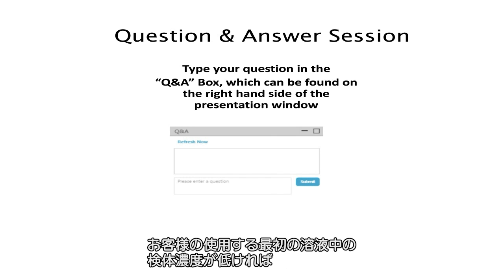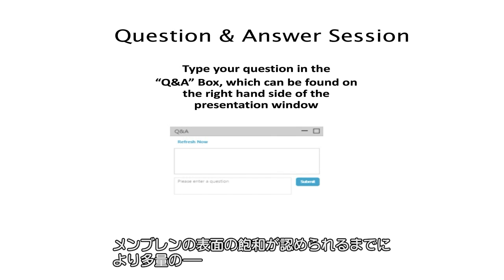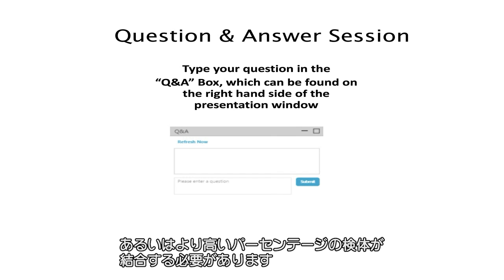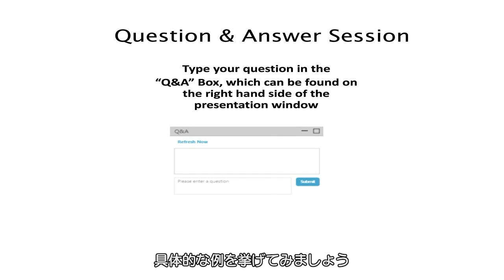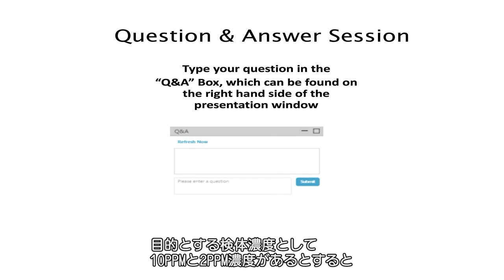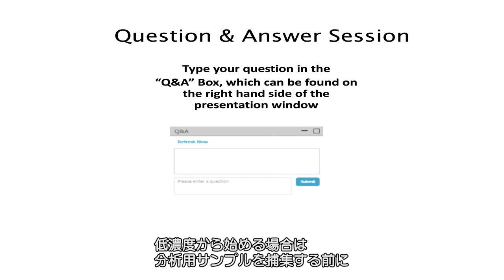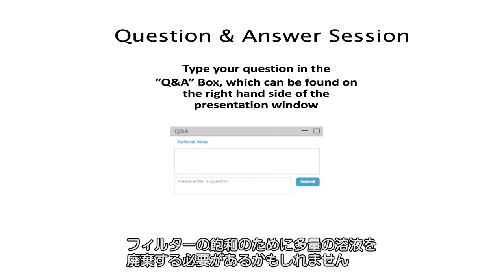If your initial concentration of analyte in your starting solution is lower, then it means a higher percentage of your analyte would need to bind before you can see full saturation of your membrane surface. So what this means in practical terms is, say for example, you are working with a concentration of 10 ppm versus 2 ppm for your analytes of interest. You might have to discard a larger volume of the solution before you collect a sample for analysis when your starting concentration is low, because that's what helps the filter to be fully saturated.